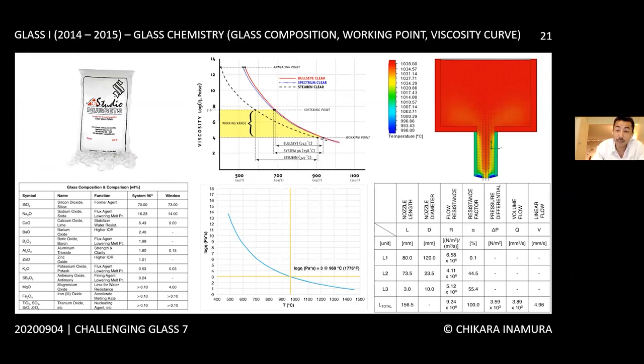Glass chemistry plays an important role in determining the control parameter for each thermal zone. We used the commercially available soda lime glass nuggets called System 96 at the time. The glass composition is similar to the soda lime window glass, but has additional additives that provide extra brightness and longer working range suitable for glass blowing.